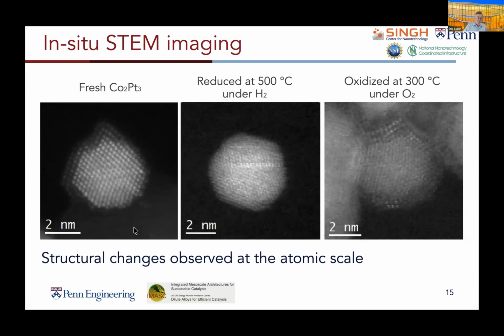If we also look at this at atomic levels of resolution, we see that in the initial stages, the cobalt that's segregated to the outer surface forms in the Co2-Pt3 phase. But if we go through and reduce that, we see a homogenization of the sample where the platinum and the cobalt are more generally agglomerated. But if we do the reoxidation, we actually see a very coarse oxide layer on the outer surface. Again, this is all taken at 300 degrees C in an oxidative environment. And so this feature here is again consistent with the Co3O4 that was observed in the X-ray spectroscopy.